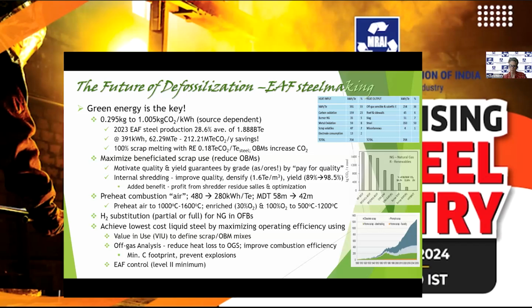And then, as I said earlier, pay for quality, improve your yield. You can also use preheated combustion air. We used to have a system when I was with Air Liquide, and we saw reductions from 480 to 280 kilowatts per ton. And the meltdown time came down 16 minutes using preheated air or oxygenated air. Hydrogen substitution, of course, in the oxy-fuel burners is an opportunity also to reduce further, but that's a minimal amount compared to the power reduction.